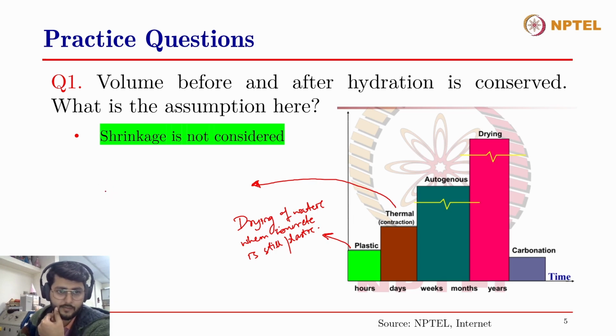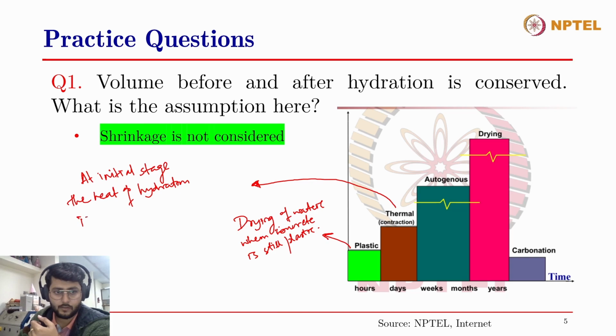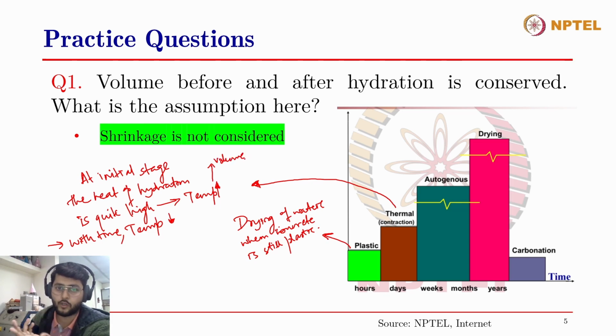Thermal shrinkage is basically when water is initially added to the concrete, the chemical reactions, the dissolution and precipitation, undergo at a very high rate, and therefore the heat of hydration at the initial stage is quite high, hence the temperature is high inside the concrete, right? But with time the temperature reduces. When the temperature is high, the volume is higher because the volume expands when the temperature increases.